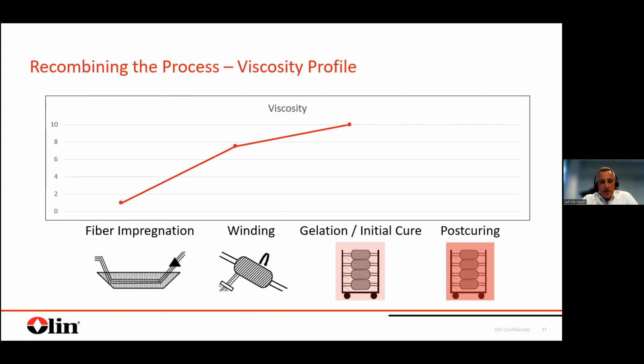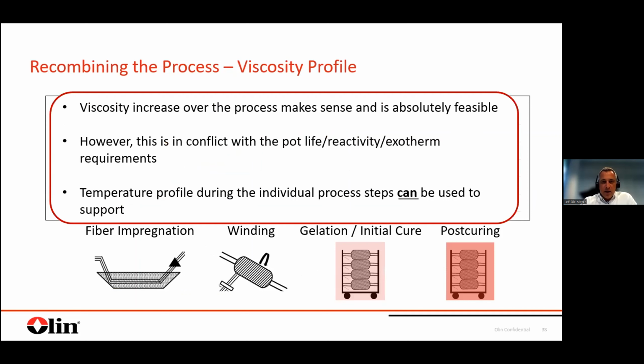However, then you expect a very steep increase, or you could expect a steep increase towards the winding process, and then in the end, upon gelation and cure, you expect it to be on the pretty high side. So overall, this viscosity increase over the process makes sense. I mean, chemically, you're increasing the network density, the degree of cure over the process steps. So in general, it makes sense.